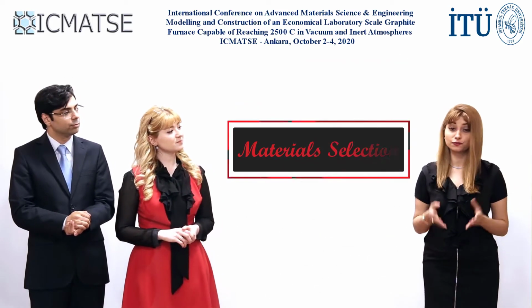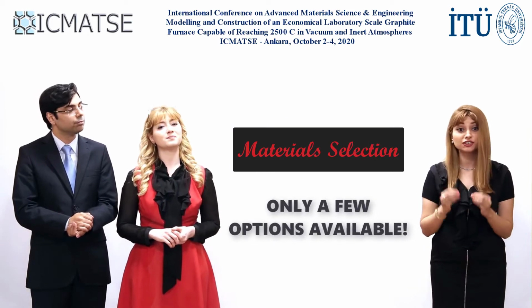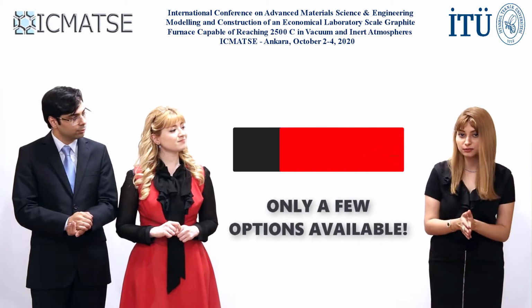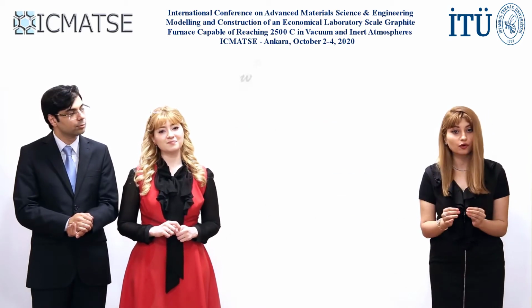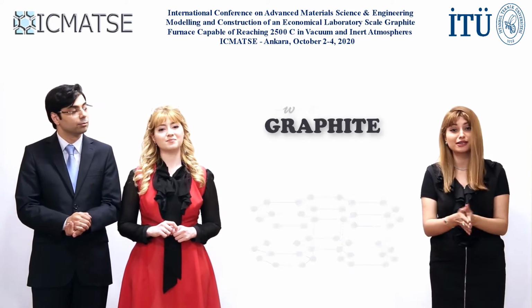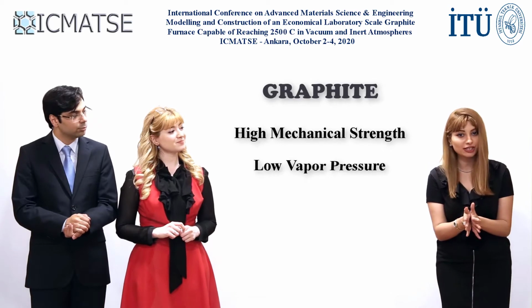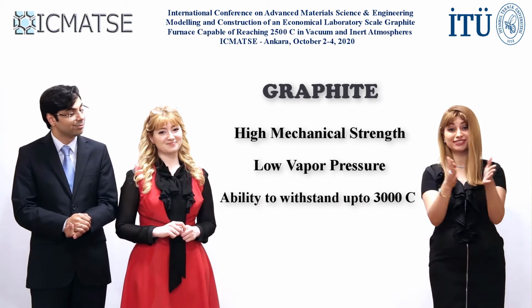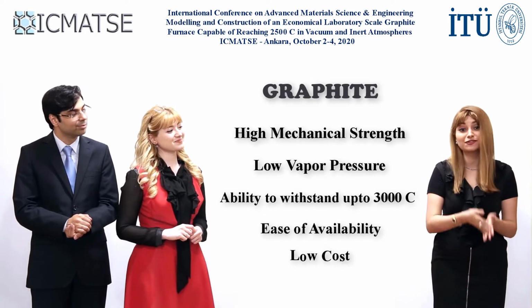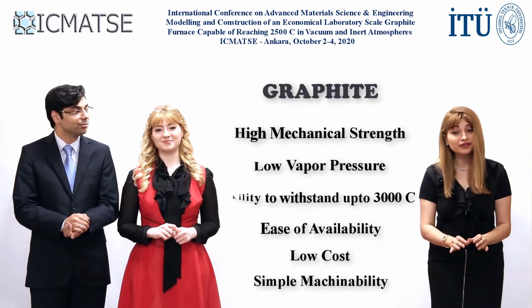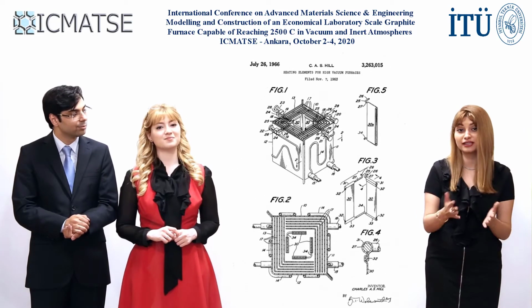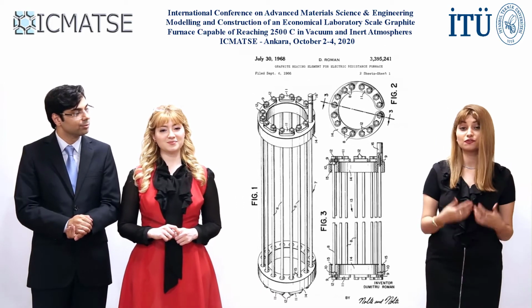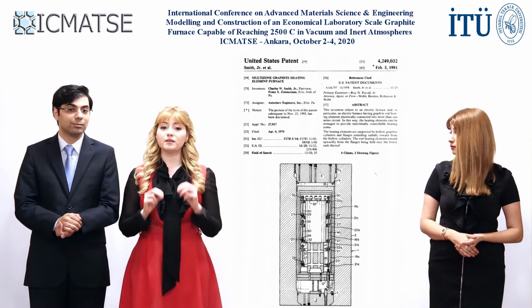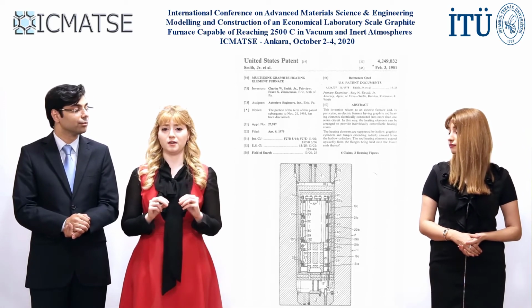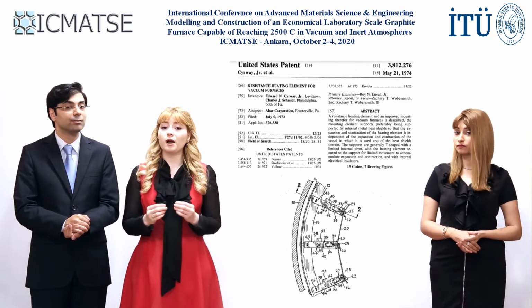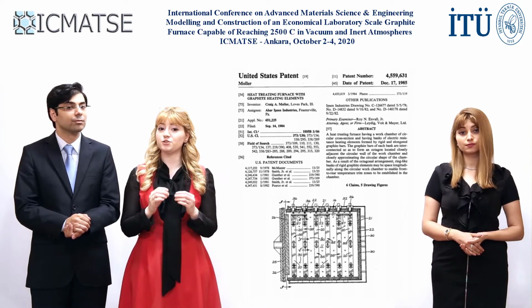When it comes to material selection for the hot zone, there are only a few options available which can fulfill the requirements we have discussed, both in terms of cost and material properties. Therefore, we proceeded with graphite due to its impressively high mechanical strength at high temperatures, low vapor pressure, ability to withstand temperatures up to 3000 degrees Celsius, ease of availability, low cost, and rather simple machinability. There are very interesting graphite hot zone designs either published in academic literature or patented, some of which are widely used industrially. However, upon reviewing them in detail, we found that there are only a limited number of hot zone designs available that meet the requirements of a compact lab-scale graphite furnace for research and development purposes.